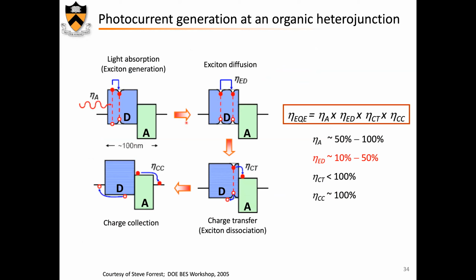So the various events that take place here. Here you have absorption of a photon, creation of an exciton, and these excitons may or may not diffuse to the interface between the donor and the acceptor. So there is light absorption, there's exciton diffusion, and each, of course, has its own probability depending on the structure and so on. At this interface, if the exciton gets to the interface, there is a chance that the electron will be transferred to the lower energy LUMO on the acceptor, and eventually the electron and the hole then go their own ways and are collected, the hole to the left and the electron to the right.